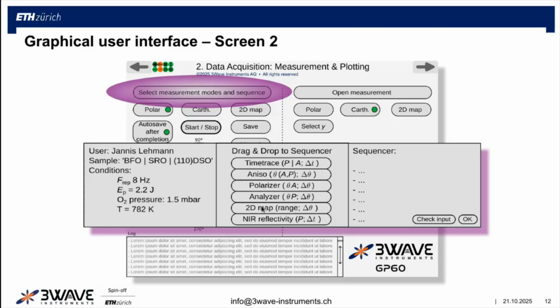You can also measure a full two-dimensional map where you change both, subsequently, the polarization state and the analyzer position, and then you have a two-dimensional polarization map. Or you can monitor just the infrared reflectivity in case you have, for example, a metal-to-insulator transition. Depending on your thickness or temperature, you could go just for the infrared reflectivity.